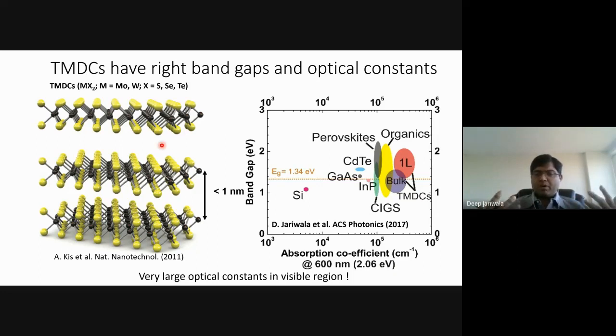Semiconducting materials are important for all optoelectronics and electronic technologies. So we started thinking that if they are semiconductors, what is their band gap and what is their ability to harvest light? This is how my group and I got interested in them. What we found is that they have a band gap very close to about 1.34 electron volts, which is ideal for solar light harvesting.